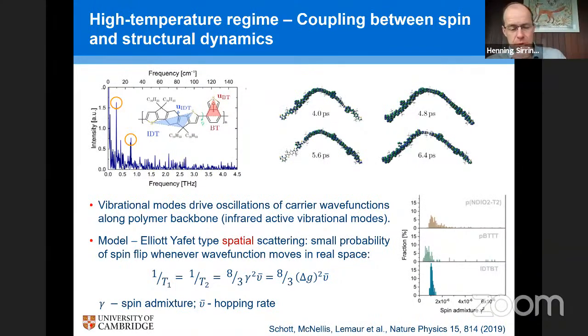That's a very, very good question. We've been trying to quantify the strength of spin orbit coupling in this system, and maybe I skipped a little bit the details here for this mechanism of Elliott-Yafet spin scattering that we think is responsible for the spin relaxation near room temperature. That mechanism, of course, is proportional to the strength of what we call the spin admixture, which is a measure of the strength of the spin orbit coupling.